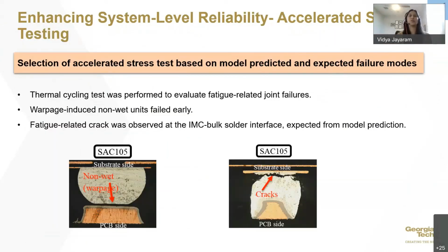So the high stress locations were at the corners of the chip and board level interconnections. The next part was to run some accelerated stress tests to understand what kind of failures we see. And some of these images, I had used to even explain the different types of failure modes and mechanisms. So we did see two types of failures. We saw process-induced failure, where because of high warpage at chip level, we did not have good contact of the corner bumps to the copper pad. And we also saw fatigue-related failure mode, where stressing it with thermal cycling test over time led to solder crack at the IMC bulk solder interface, which was the weakest point.